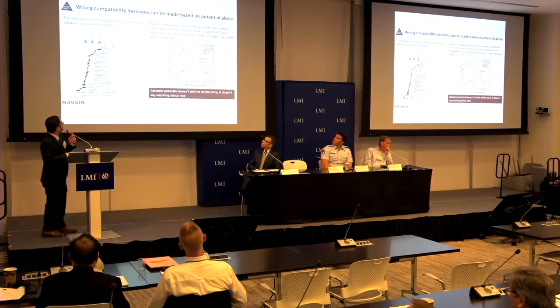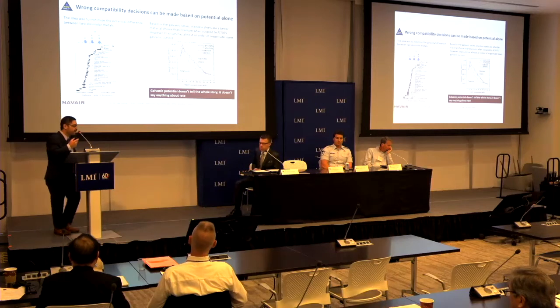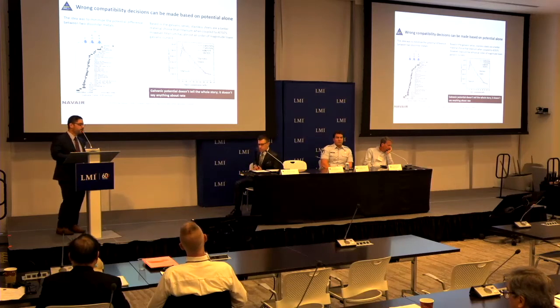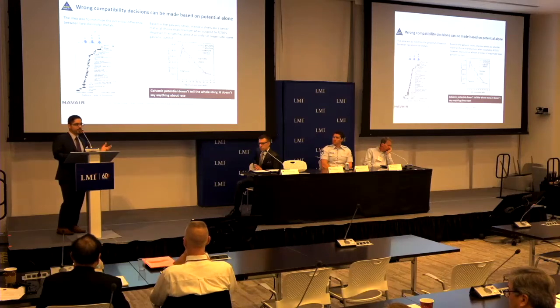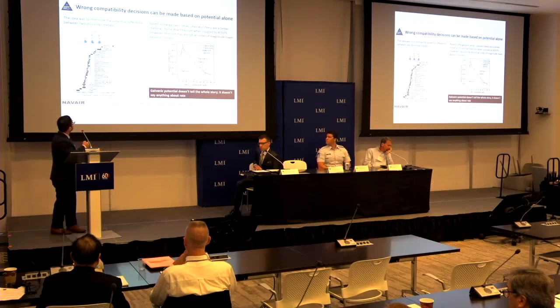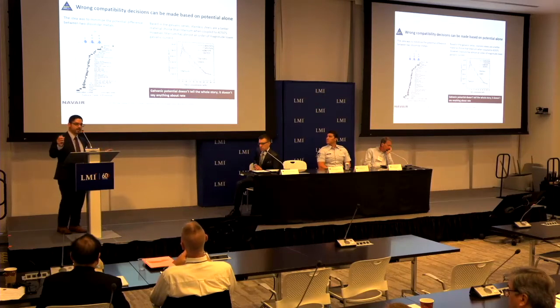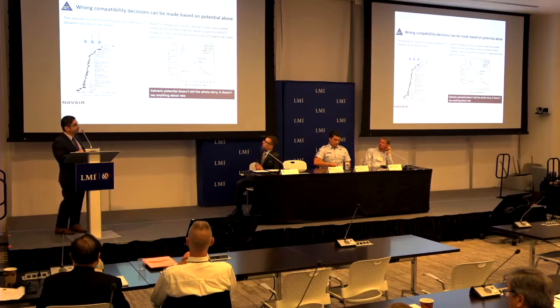So again, going back to the table of potentials, right? So the idea really was to minimize the potential difference between two dissimilar metals. And if you were to use the galvanic table of potentials here on the right, it would tell you that you can match stainless steels, that they're a better choice to mate with aluminum, right? Because their difference is smaller, right? So it would tell you don't pair anything with titanium, right? Don't pair aluminum with titanium. That's a bad choice.